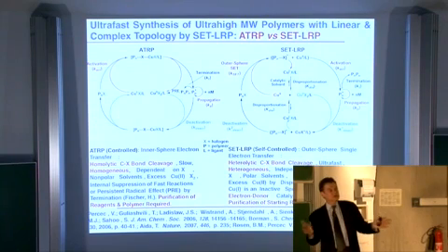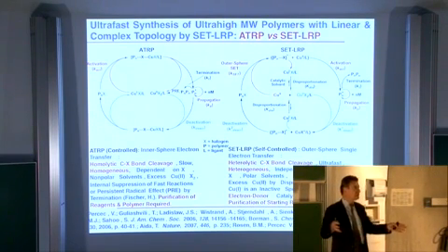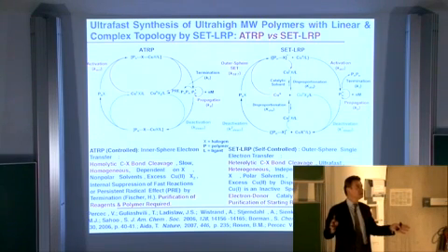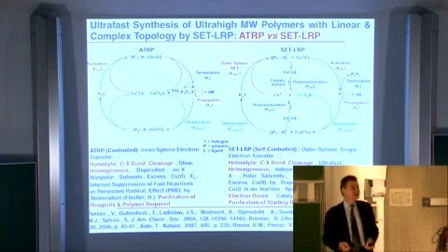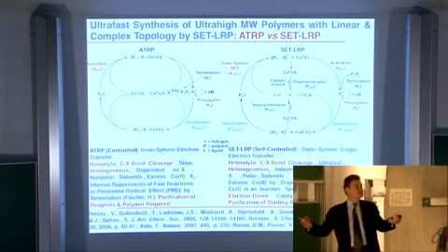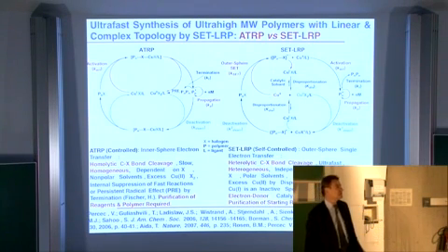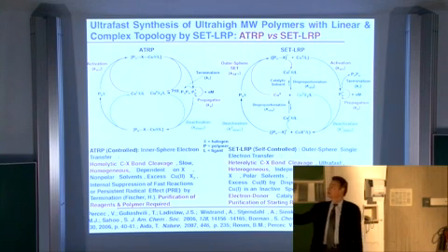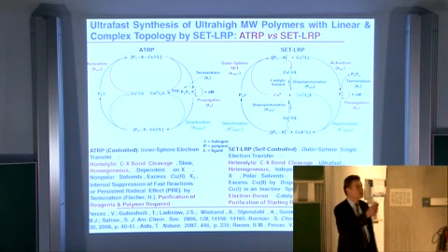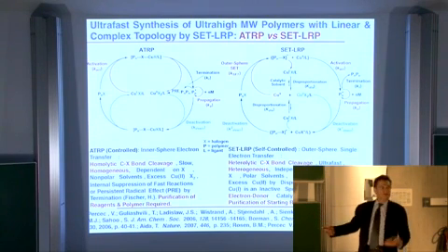So this is a heterogeneous reaction, and heterogeneous catalysis is surface determined rather than concentration dependent. The copper-0 that is generated in situ is an atomic species that starts agglomerating, but atomic species are much more reactive than the wire or the 5-cent coins that you use in the reaction mixture. As a consequence, this is a very fast reaction.